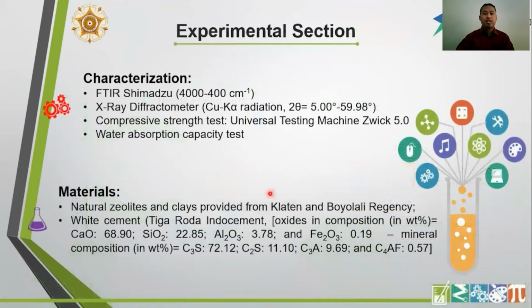The materials used in this study include natural zeolite, natural clay, and white cement with composition of tricalcium silicate about 72%, dicalcium silicate about 11%, tricalcium aluminate about 9%, and the last is tetracalcium aluminoferrite about 0.5%. The prepared composite was also characterized using infrared spectroscopy, X-ray diffractometer, compressive strength test, and water absorption capacity test.